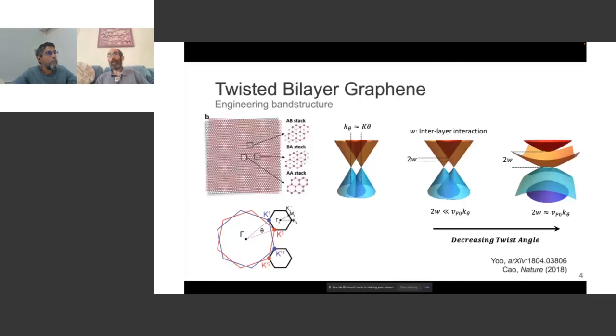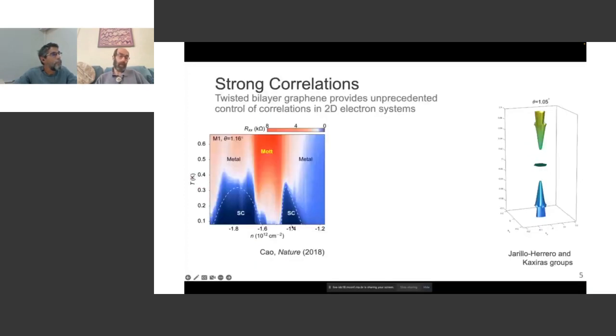But I'd like to focus on something really exciting that happened about 4 years ago. The group of Pablo Jarillo-Herrero at MIT observed that in a system like this, as you tuned the density of electrons in the system, which it turns out you can do in a way inspired by transistors in computer chips with a nearby electrode called a gate, at very low temperatures, there were densities at which the material became superconducting and densities where it had an unusual type of insulator that they identified as being caused by electrical correlations. And so that was really, really exciting and led to a lot of other groups trying to work on this. There was a relatively soon another group reproduced this work and extended it in some ways. This was at Columbia. Matt Yankowitz was the first author of this.